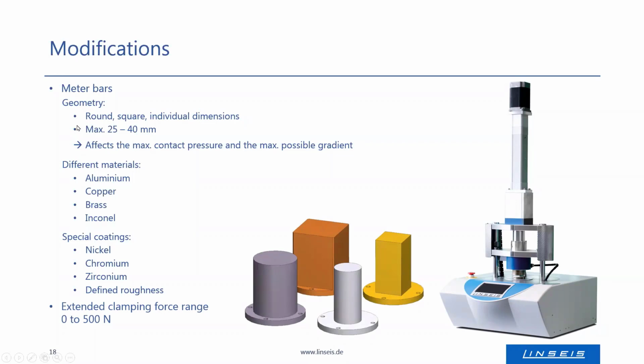Typically, these meter bars have a size between 25 and 40 millimeters. What is important here is that the size and the shape of the meter bars affects the maximum possible contact pressure and also the maximum possible gradient over the sample.